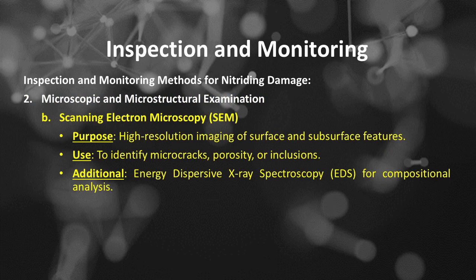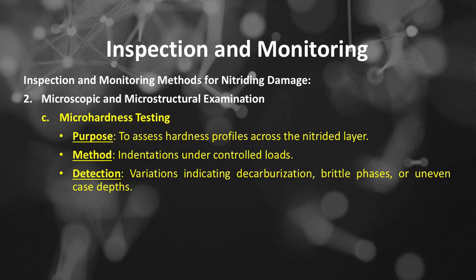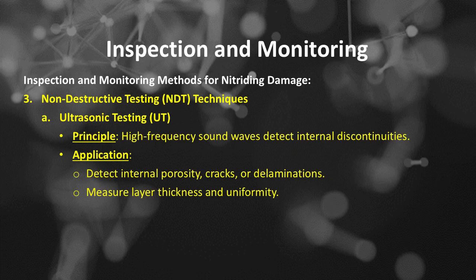Number B of microscopic and microstructural examination is scanning electron microscopy, or SEM. Its purpose is high-resolution imaging of surface and subsurface features, used to identify microcracks, porosity, or inclusions. An additional method is energy dispersive X-ray spectroscopy, or EDS, for compositional analysis. Number C of microscopic and microstructural examination is microhardness testing. Its purpose is to assess hardness profiles across the nitrided layer. Method: indentations under controlled loads, detecting variations indicating decarburization, brittle phases, or uneven case depths. Number 3 of inspection and monitoring methods for nitriding damage is non-destructive testing, or NDT, techniques.